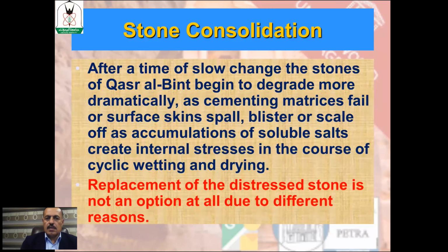Stone consolidation again is needed because the stone of Qasr al-Bint has decayed to a degree that sometimes it needs to be strengthened. The strength of the stone needs to be restored, and the only possible technique to do this is by using a consolidant that's well tested and proved to perform well in the laboratory and field testing program. As I mentioned, the replacement of the distressed stone is not an option, or should be the last resort, due to the importance and significance of this monument.